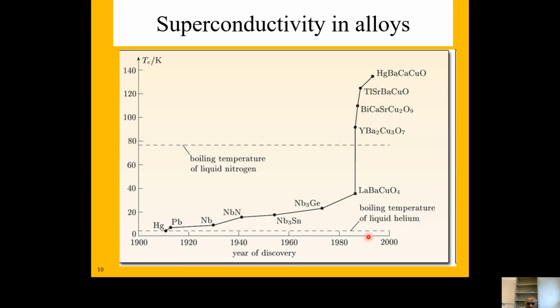Not until around 1985 or so did they find this lanthanum barium copper oxide, a ceramic compound oxide, that showed superconductivity close to 40 Kelvin. That was a big discovery, because people never expected the Tc to be that high, close to 40 Kelvin.